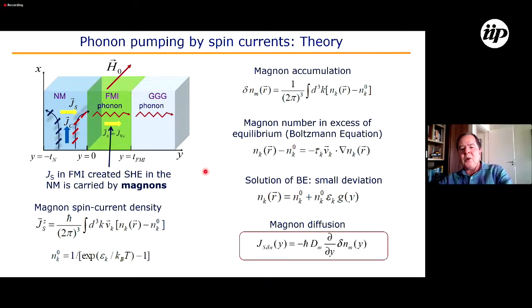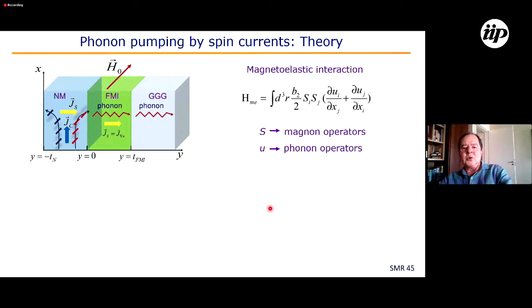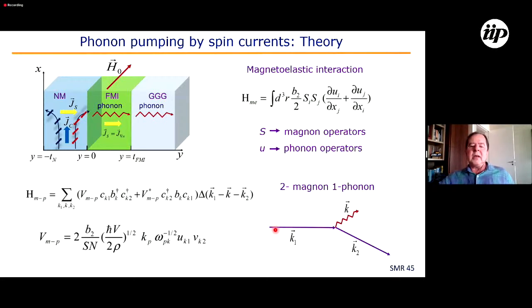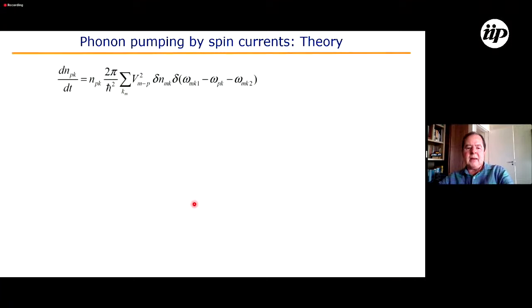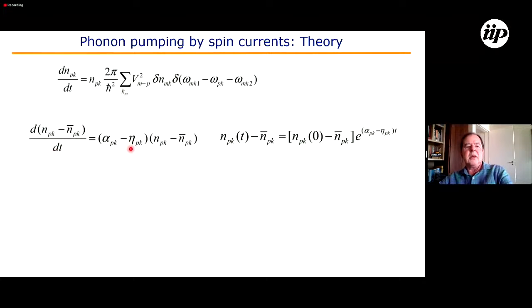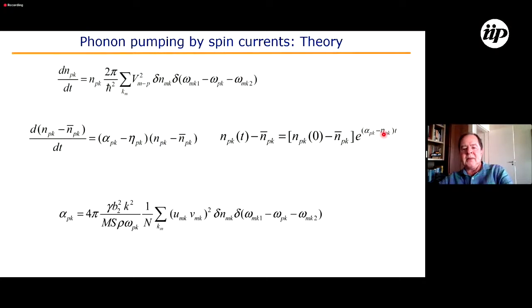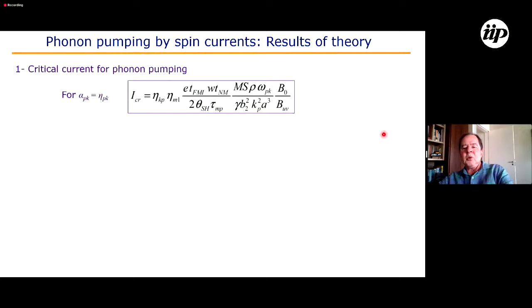We use the Boltzmann equation to find these solutions. We introduce the coupling between magnons and phonons, and the explanation is this. The spin current in the YIG film is carried by magnons. Magnons can be scattered into another magnon and a phonon, and we can calculate the probability of excitation of phonons by Fermi's rule. Using Fermi's rule, we show that the change in time of the occupation of phonons is given by this expression, so that when the pumping rate is larger than the relaxation rate, we have excitation of phonons.